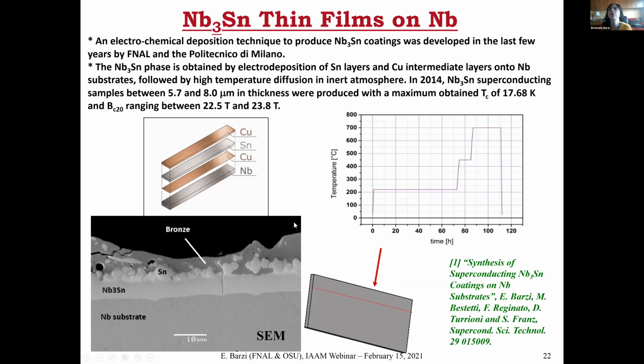And so this opens the way to a lot of other applications, for instance, superconducting magnetic shielding, or superconducting radio frequency cavities. Now all the rage is on coating niobium cavities with niobium-tin, and they do it through vapor tin diffusion in large ovens, but it's not very well controlled. So they put the cavity in there with a lot of tin sources, these big shell cavities, and the tin diffuses in the niobium. But of course, you can imagine that with electrochemical deposition, we would have a much better control.